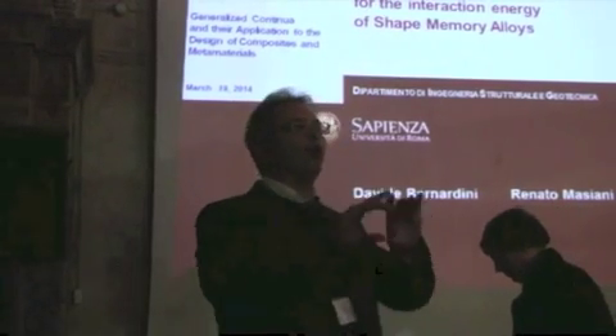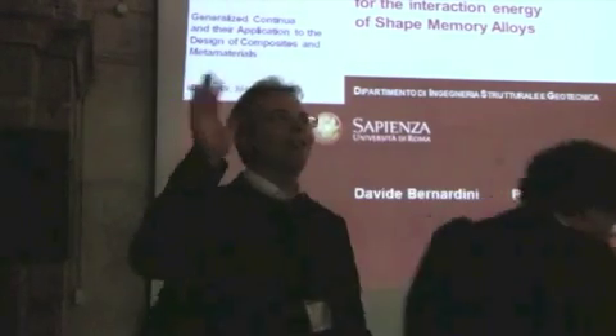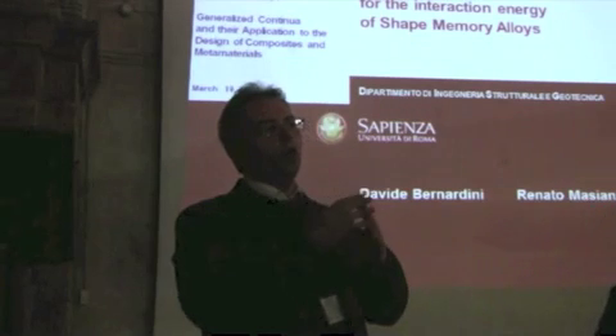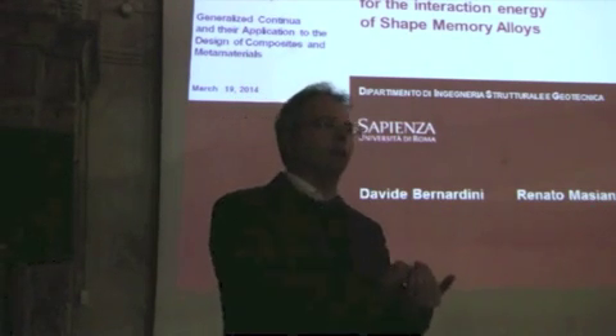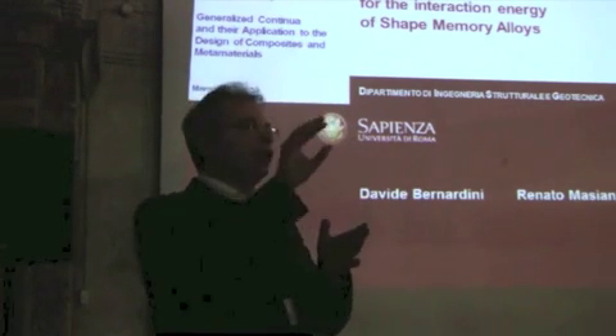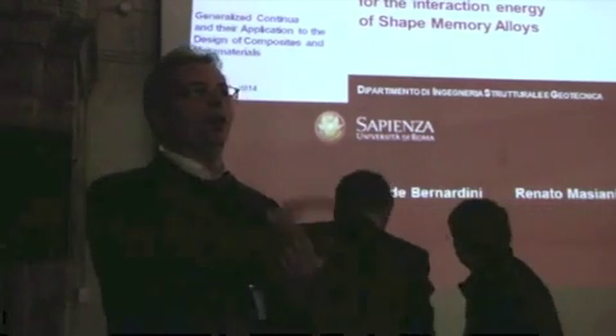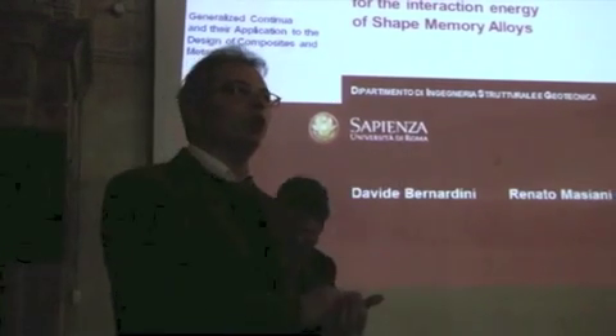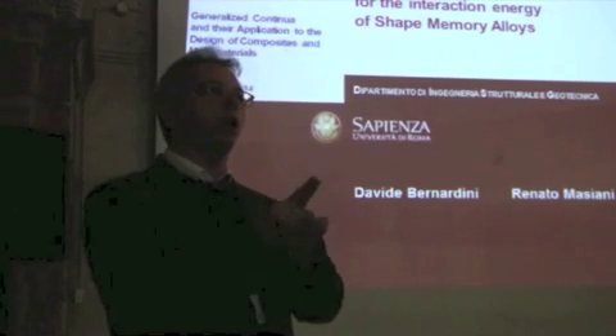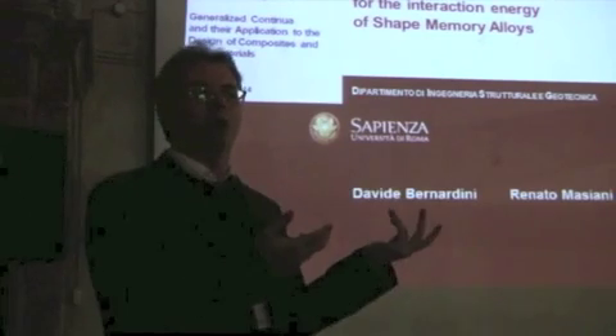So your final model, this was, I think, good in microscale, and there was a very important assumption that you can assume that the first fiber results in the failure of the last fiber, or something in between. But the model was abandoned and this is the simplest version of a global sharing rule. Of course, there are hundreds, thousands of papers where they actually have local sharing rules. Now, it really depends on what type of statistics you embed inside, what you were mentioning. I may not be aware exactly of their work, but I have seen it in all sorts of flavors, and the key is really what type of disorder you put inside and what type of interaction you enforce between neighboring links. But this is mostly like a textbook example for me.